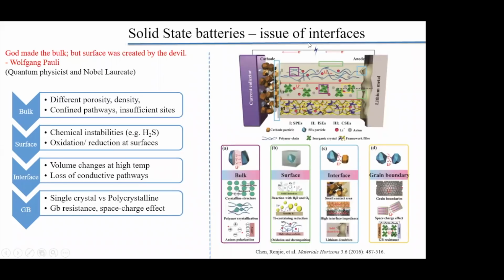So to summarize the issue of interfaces, let's put those two things together. This is from the same paper. We have bulk interfaces. At the bulk interfaces, you need to solve the problem of porosity. Different materials have different density, and you need to make sure it's a seamless mixture. You need to make sure there are no confined pathways. For example, lithium should have sufficient sites to go from one side to the other.